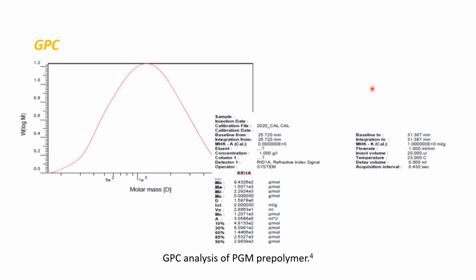As the results performed by Wang and coworkers, the PGM prepolymer shows low molecular weights, around 943 for Mn and 1507 g/mol for Mw, and a good polydispersity index. Modification to increase Mn and Mw and retain a strict PDI needs to be done. The prediction is by addition of 1,4-butanediol, due to the result from previous work conducted by Chen and coworkers to synthesize prepolymer, who succeeded in obtaining around 75 kilodalton for Mn and 1.98 for PDI.